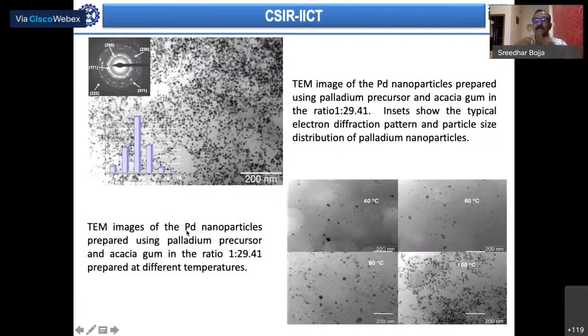Then we tried to look at the solutions at different temperatures in a transmission electron microscope. At different temperatures they are all assorted, but at 100 degrees you see that they have attained uniform size of about 8 to 10 nanometers. All throughout the grid there is no agglomeration, the particles are not in a big lump. They are nicely dispersed all throughout the grid.